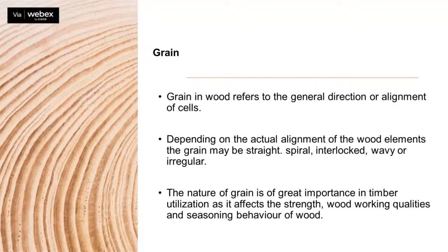The nature of grain is of great importance in timber utilization, as it affects not only the strength, but also the woodworking qualities as well as the drying behavior, because if the grains are not straight, when you dry the timber before carving, there can be a lot of deformation, and that can add to loss of material.